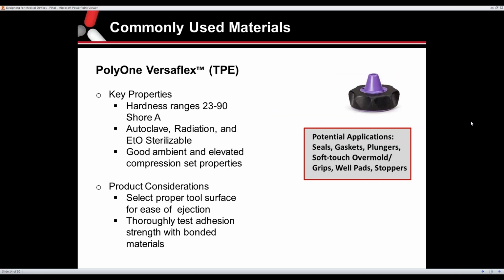Next is actually a PolyOne product. Versaflex is our TPE material, a thermoplastic elastomer. This material has a wide range of durometer, so it can be pretty soft to quite rigid, but it can be autoclaved, it can be gamma sterilized as well as ETO, and it's got really good compression set properties. So it makes it ideal for gaskets, seals, things like syringe plungers, and soft touch overmold, so grips and things like that, as well as well pads or stoppers. So you can really get a lot of uses with this.